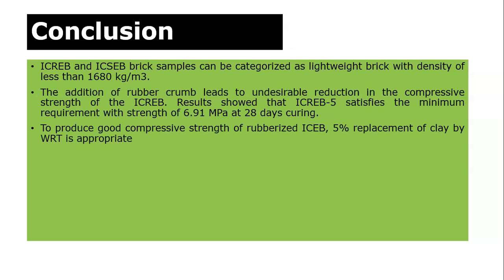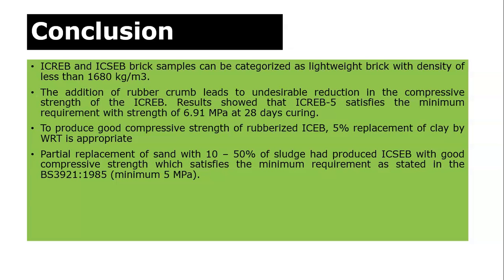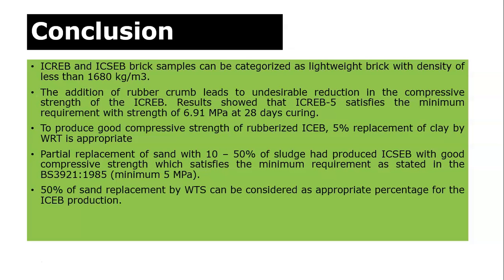Hence, to produce good compressive strength of rubberized ICEB, 5% replacement of clay by waste rubber tire is appropriate. And partial replacement of sand with 10 to 50% of water treatment sludge has produced ICEB with good compressive strength, which satisfies the minimum strength requirement as stated in the BS 3921, which is a minimum of 5 MPa. And 50% of sand replacement by water treatment sludge can be considered as the appropriate percentage for ICEB production. This would lead to lower production costs besides minimizing environmental impacts due to sludge disposal.